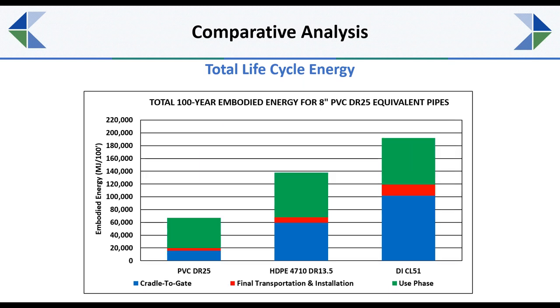For the 8-inch, which just as a conversion, 8-inch is approximately 200 millimeters in metric. But for that 8-inch diameter, for the lower flow or lower pressure condition, you can see that it's a little bit different. It's roughly 52% less than HDPE and roughly 65% less than the ductile iron pipe.